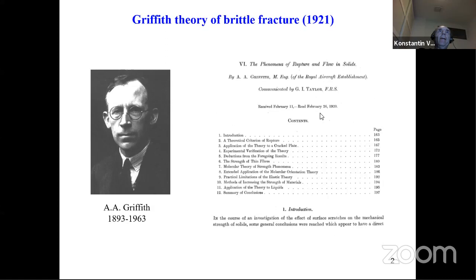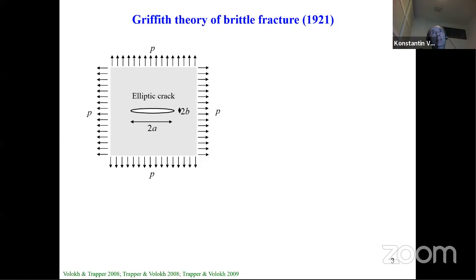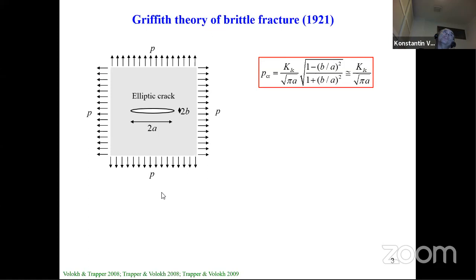It is the basis for so-called linear fracture mechanics and for its generalizations. Since the paper is very important, I would like to show you the main result. What Griffith did was consider an elliptic crack in plane loading under hydrostatic tension. The solution for this problem was obtained by Inglis before Griffith, but what Griffith did was consider a global energy balance and found the critical pressure under which the crack becomes unstable.